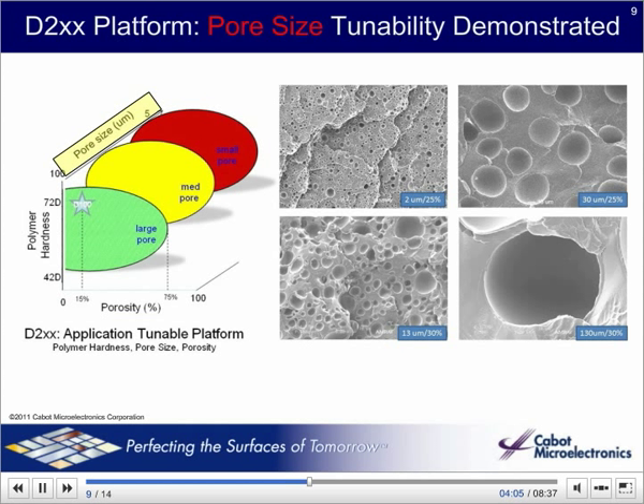As I mentioned on the last slide, we can also independently control the pore size, in this case ranging from 2 microns to 130 microns. To put these sizes in perspective, a 130 micron pore is 1,000 times bigger than a 130 nanometer feature on a chip. So you can think of these asperities as huge tongues of rubber sliding along the wafer surface. Since particles are also around 100 nanometers or less, you can envision hundreds or thousands of particles absorbed onto a single pad asperity. It is probably unlikely that the bare rubber contacts the wafer surface. More likely there are particles and fluid riding and rolling in the gap.